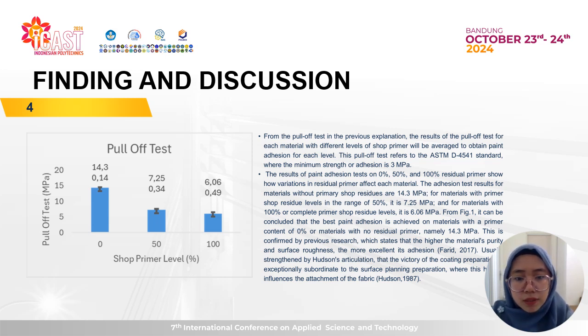The result of the paint adhesion test on 0%, 50%, and 100% residual primer shows how variation in residual primer affects each material. The adhesion test result for material without shop primer residue is 14.3 MPa. For material with shop primer residue level in the range of 50%, it is about 7.25 MPa, and for material with 100% or complete shop primer residue level, it is about 6.06 MPa. And then from Fig. 1, you can look at the diagram or graphic about the result of the pull-off test of the material.